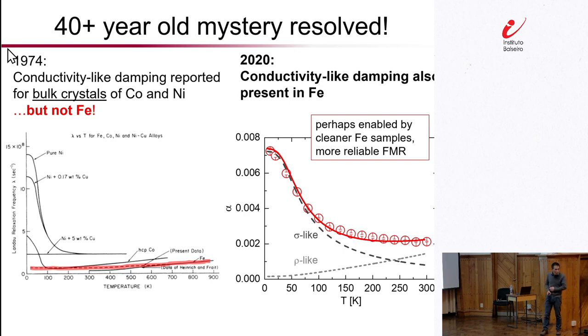Now, of course, the obvious question at this point is, why is it that we are able to see the clear signature of conductivity-like damping in iron, but not these people back in the 1970s? Well, at this point, we can only speculate. One possibility is that conductivity-like damping is rather sensitive to the quality, the cleanliness of the material. So these bulk crystals, little millimeter-scale flakes of iron, possibly were not quite as clean as our epitaxial films grown under high vacuum conditions. That's one possibility.